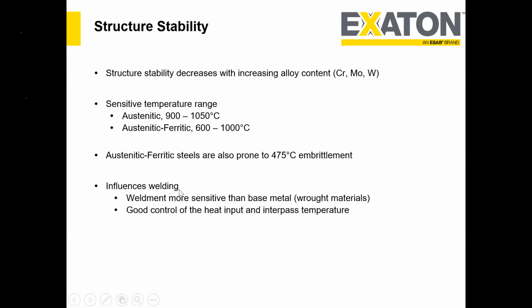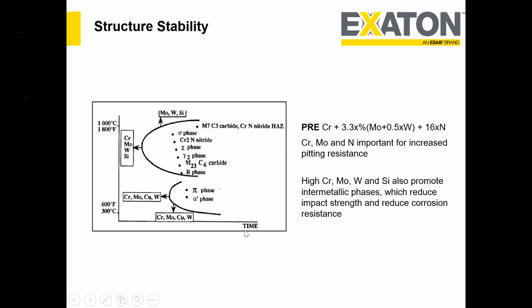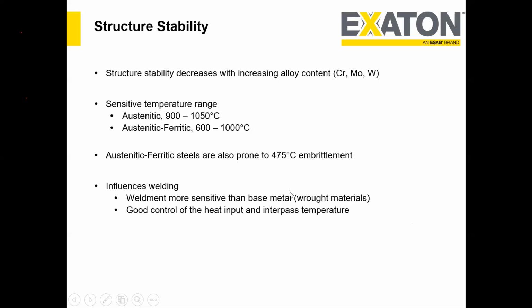And the influence of welding is important because the weldment is more sensitive than the base material, which is wrought material. For the base material, normally for plate or pipe, we do a solution annealing operation at the end of forming, where we can eliminate a lot of undesired structure or intermetallic phases, which in most cases is not possible in the weld metal. If it's a small sample, probably we do this, but imagine we make an offshore structure or a big pressure vessel. It is almost impossible to do solution annealing for such a critical component.